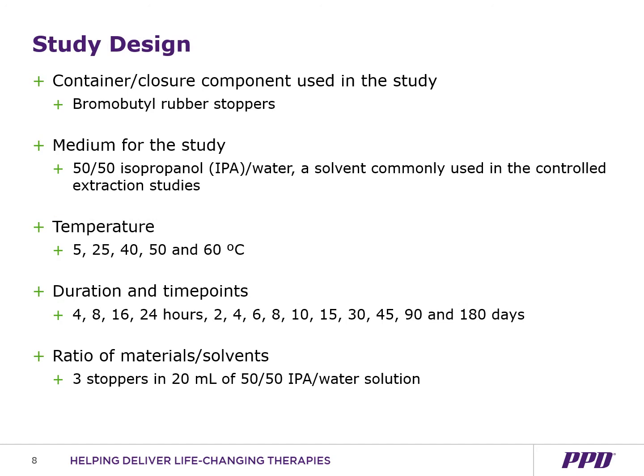So the initial study, the container closure component we investigated was bromobutyl rubber stoppers. We looked specifically at BHT from the rubber stoppers sitting still in incubation and allowing only time or duration and temperature as factors for extraction. The solvent chosen was 50/50 IPA water, a solvent that is commonly used in extraction studies. The temperatures chosen were 5, 25, 40, 50, and 60 Celsius. The duration and time points chosen are listed out on the slide, but range from 4 hours to 180 days. Lastly, we used 20 mLs of IPA water solvent as an exposure with 3 stoppers for each sample.